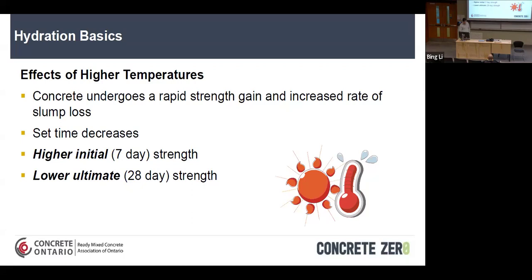You get a higher initial strength when you heat your concrete, but you'll get a lower ultimate 28-day strength. And that has to do with the chemical process. You're gaining more tricalcium silicates in your first 7 days with the higher temperatures than you are the dicalcium silicates. And that is what gives you your initial high strength. But the dicalcium silicate is what gives you your ultimate higher strength down the road.